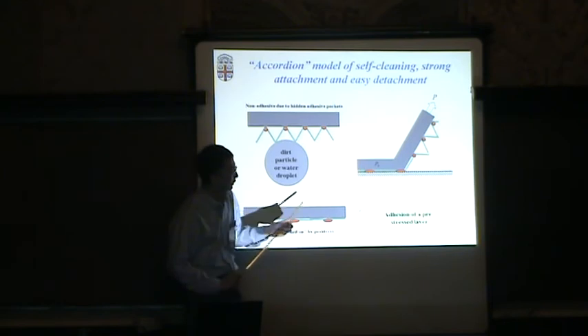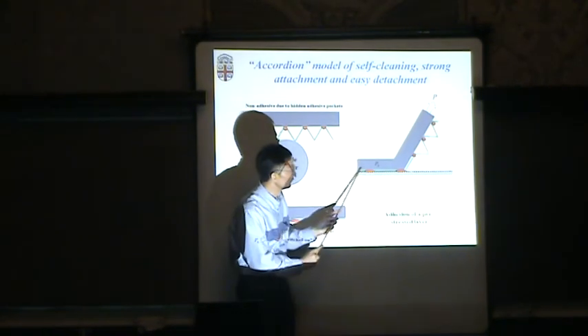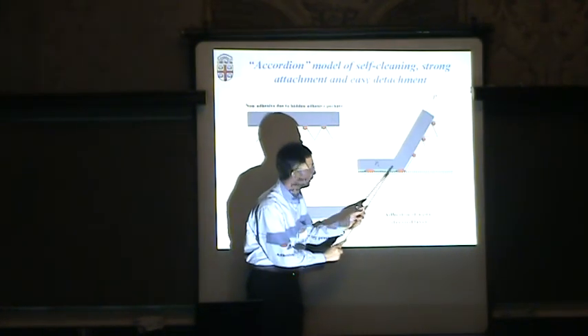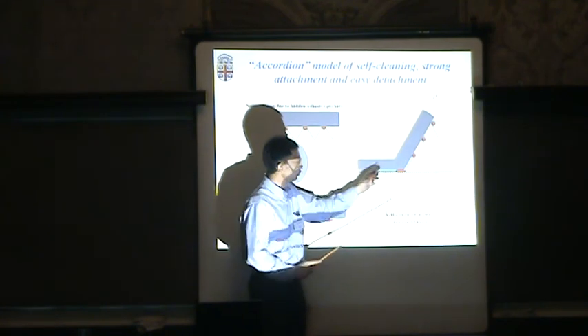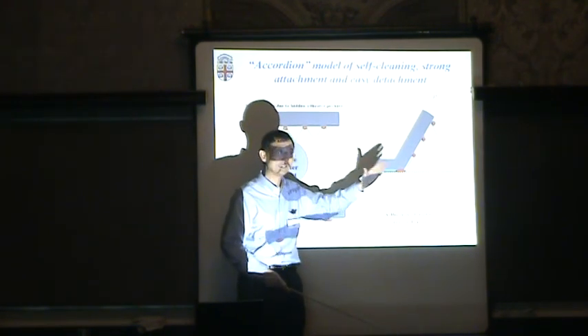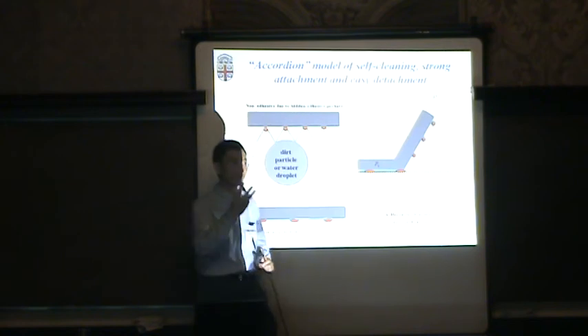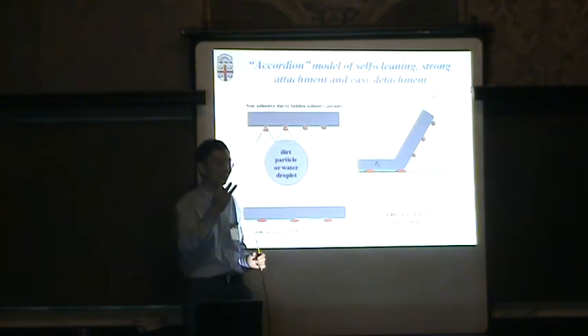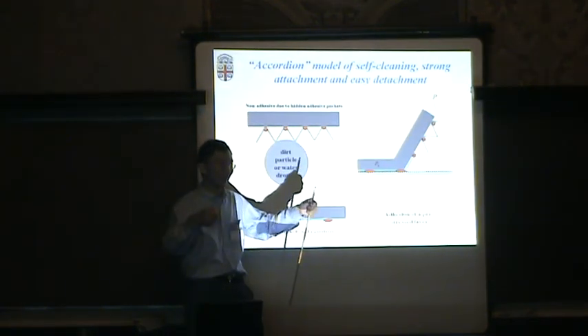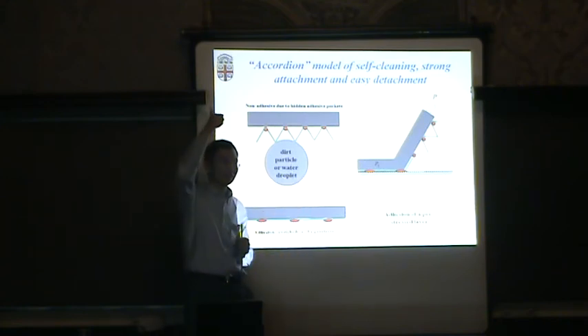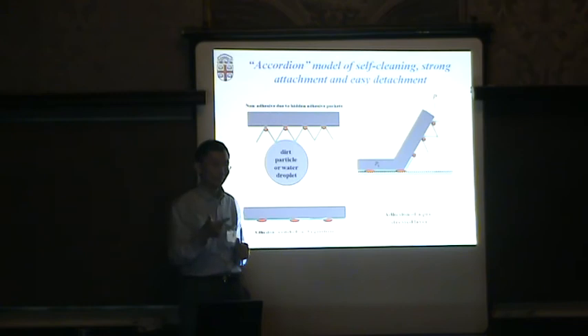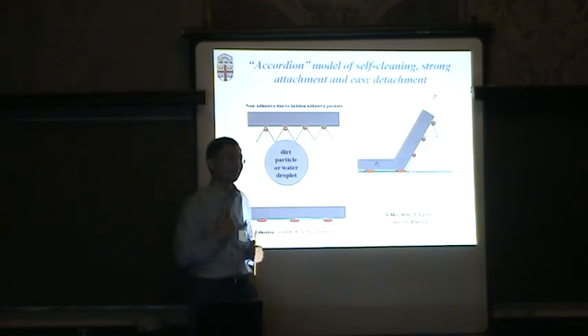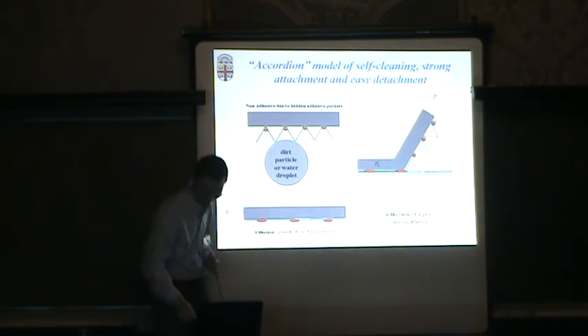But under stress, if I scratch my feet, I apply a pre-stress, I expose these adhesive functional groups, and they become adhesive. So I turn on adhesion by putting a pre-stress here. The pre-stress also allows me to spontaneously release it. So the pre-stress has three roles. One is to expose the active functional groups. The second is to enhance adhesion at low angle. The third is to allow spontaneous release of adhesion at the critical angle.